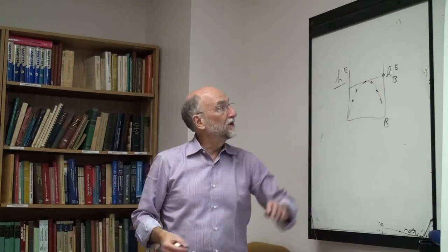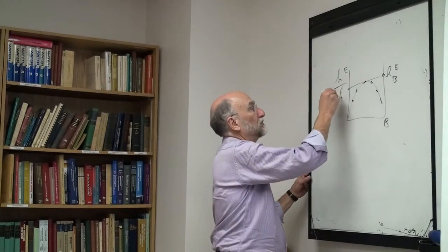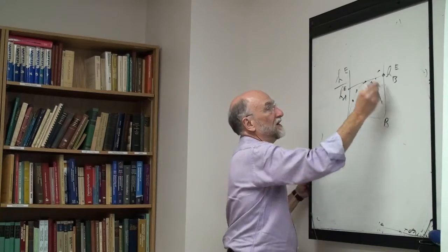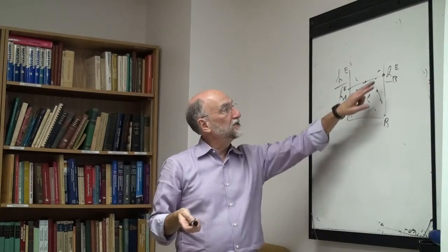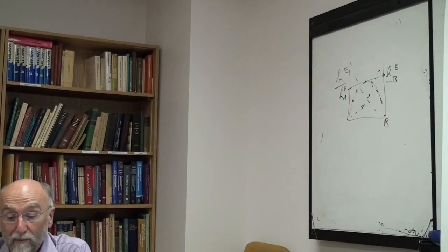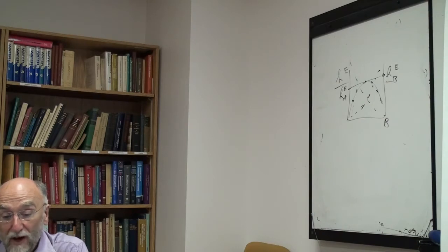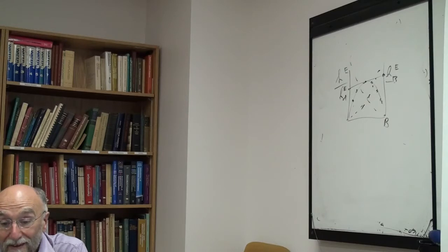So I have partial properties. Let's say I have some partial properties of A2. These are experimental points, so I have partial property experimental points. I'm trying to simultaneously fit the integral and the partial property experimental data. And the reason I can fit them in one operation is because the equations for the excess integral property and the equation for the partial property have the same coefficients.